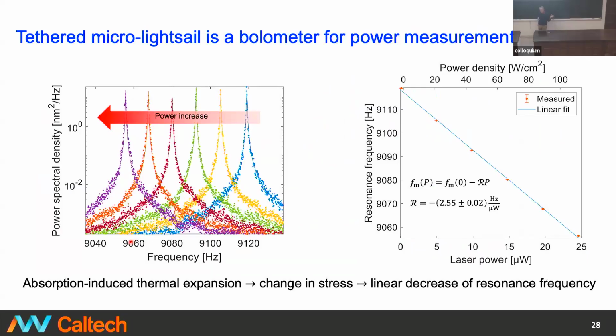The other thing that we learned is that silicon nitride is a low loss material, but its loss is not zero. It's in the 10 to the minus 4 range or so. If you crank up the power, you will see some heating that changes the compliance of the material itself. Those springs that are springy and therefore compliant become more compliant, and we see a change in the mechanical frequency. In essence, the change in the resonant frequency is a very precise bolometer. It's a power measurement that tells us exactly how much optical power was deposited in the sample. Of course, we think we know the incident optical power and the reflectance, but this has turned out to be a very precise measurement of the actual power dissipated in the material and reflected.